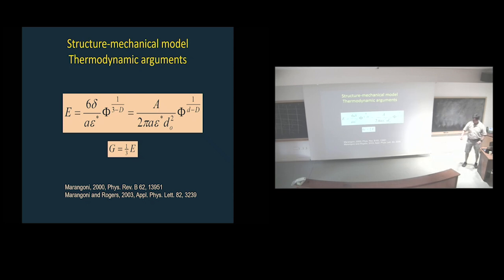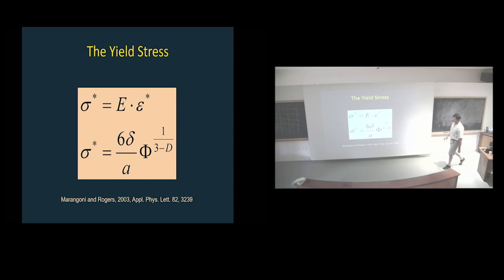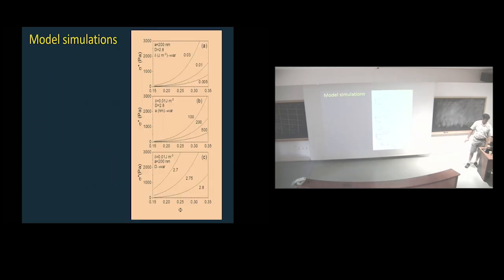And I don't like that term. And this is very classic one-dimensional compression, by the way. And then what I did is I just multiplied the critical strain by the modulus before, and you place the expression in terms of just the yield stress, if you can measure that. And the yield stress is very simply related to the volume term, to a fractal dimension. The interaction between particles related to an interfacial tension term is an indicator of strength of interactions, and the size of your primary structural unit. Doesn't get easier than that. And it works really well.